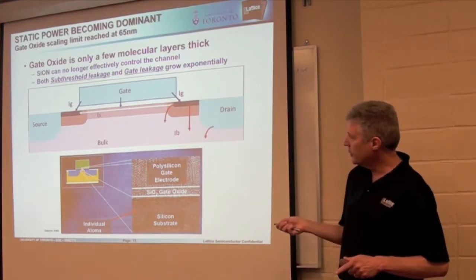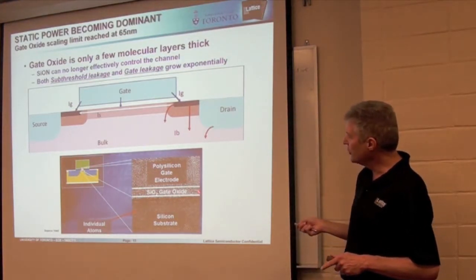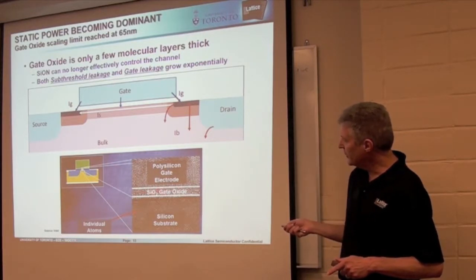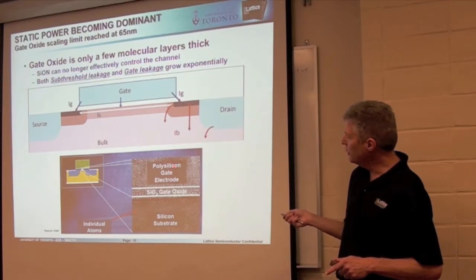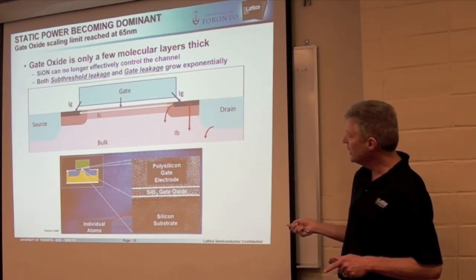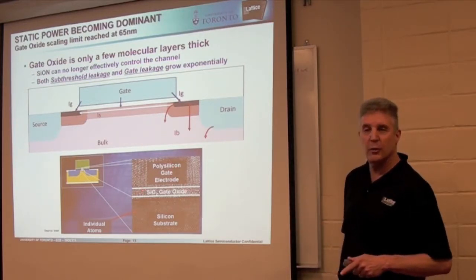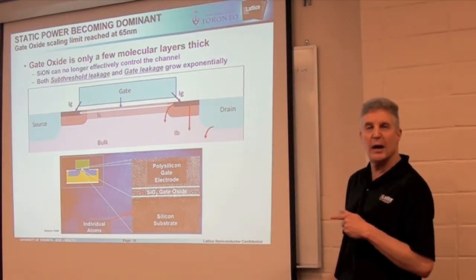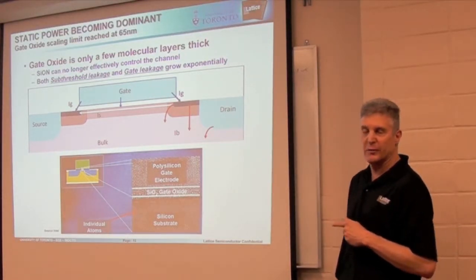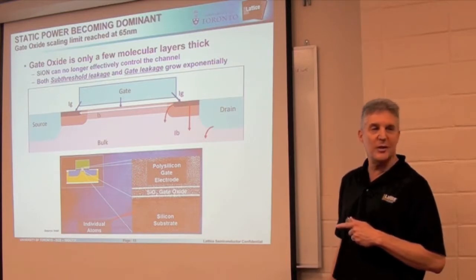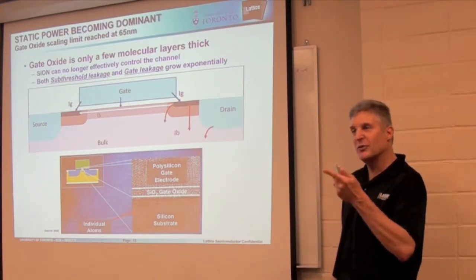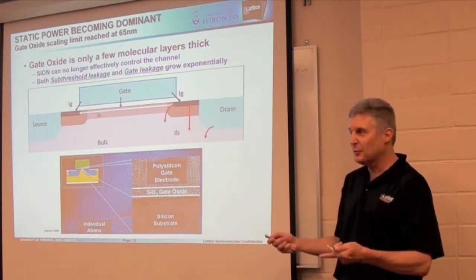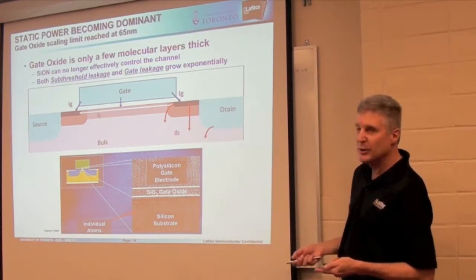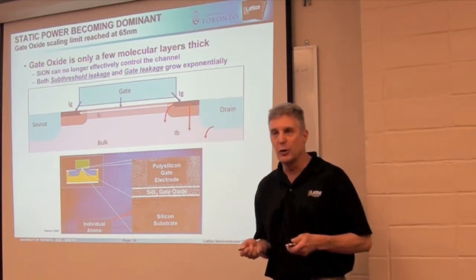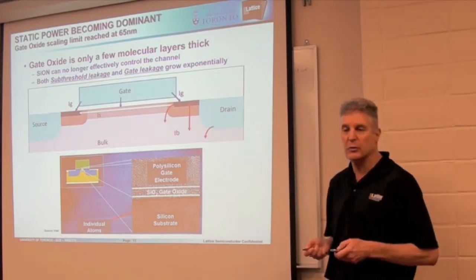TEM of a cross-section of one of these gate regions, and you can see the silicon dioxide area here, silicon gate area below the gate and above the substrate. And these dots here are actual silicon atoms. This is now about 6 atomic layers of oxide. And so you can see going from 6 to 5 is a significant decrease. And at 5 atomic layers, basically it's no longer acting as an insulator. It's just going to punch right through.